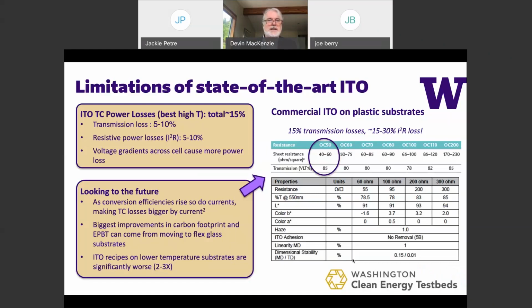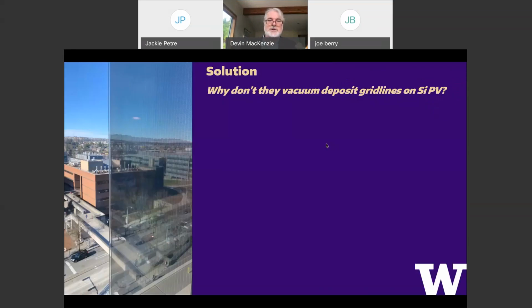So, an interesting challenge. And here's just some transparent conductor loss calculations. For good transparent conductors, you take the resistive losses and the transmission losses due to absorption in the ITO. But if you look at ITO on plastic, what's available is about 50 ohms per square at 85% transmission, which is also not great. You look at that, and we're talking about 30 to 35% total loss just from the ITO, from I squared R series resistance losses and transmission. That's a non-starter. So what do you do?